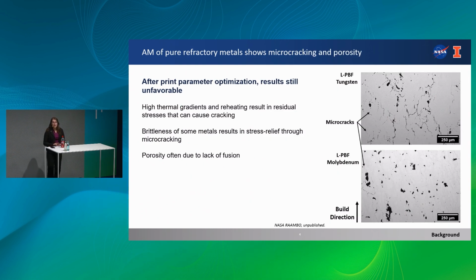But as mentioned, they are also difficult to additively manufacture. They tend to be very brittle, and so you get a lot of cracking during the fabrication process. And this is due to the high thermal gradients and residual stresses resulting from the additive manufacturing process. Additionally, a lot of porosity is seen, lack of fusion defects, and this is because refractory metals have such high melting temperatures, so it's difficult to fully melt the powder and solidify the material. So we've thought about how we can decrease this cracking that occurs during the production of refractory metals, but still keep the properties that we desire for these refractory materials.